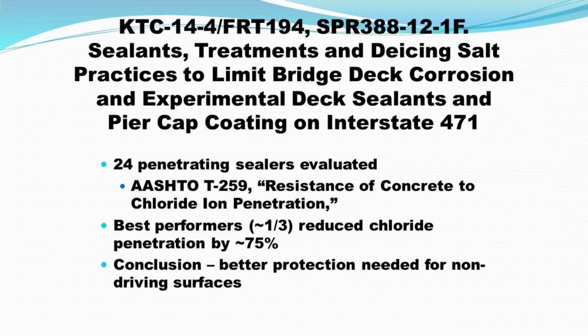The conclusion of this study was simply better protection. You need better protection for the non-driving surfaces. The best performers, about eight of the 24 tested materials, gave roughly a 75% reduction. Another third of the group gave somewhere around 40 to 50% reduction, and the remaining third of the group really gave you nothing.